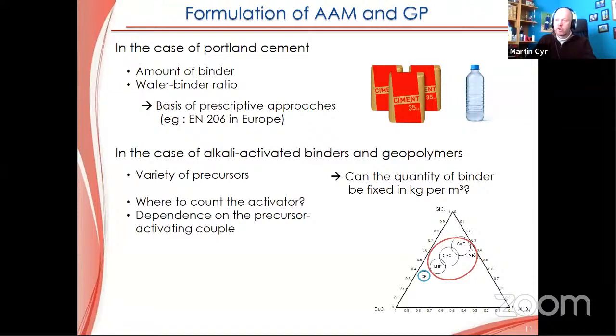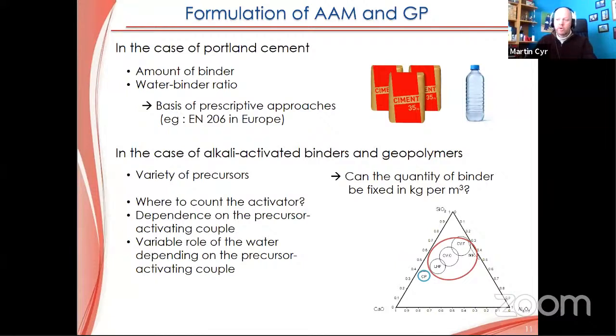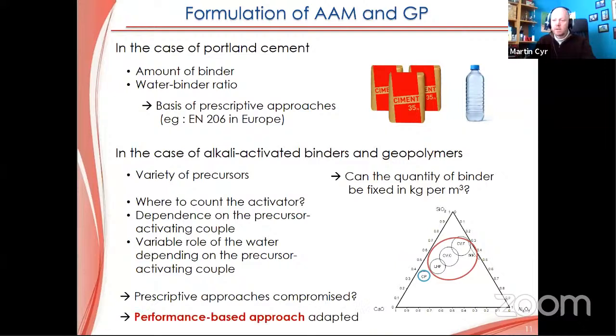And as I showed you earlier, the dependence on the precursor activator couple will also be an issue here. And of course, we have a variable role of the water depending on the precursor activator couple. If we use a metakaolin with sodium silicate or potassium silicate, the water will not enter into the structure. If we are using a GGBS, it will, because we will have some C-S-H at the end, meaning that we have very different kinds of material, and it's not always easy to understand how it works. So the prescriptive approaches are probably compromised for this, and we really think that a performance-based approach will be adapted in the future for that.